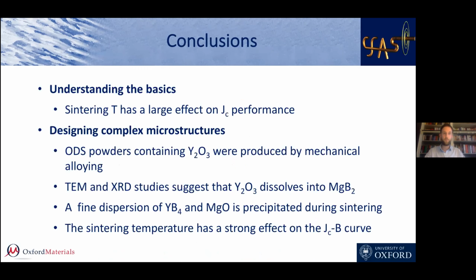We managed to show that the ODS concept can be extended to superconductors. And with TEM and XRD studies, we also showed that yttria actually dissolves nicely in MgB2 and can then be smartly reprecipitated into very small form. And in this case, because we now had another component in the system, those little particles that act as extra pinning centers, the sintering temperature has a strong effect on the JC-B curve, but not only positive, because with the coarsening, higher temperature also reduces high field properties.